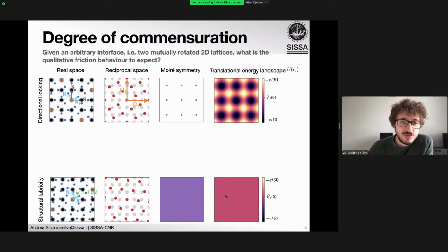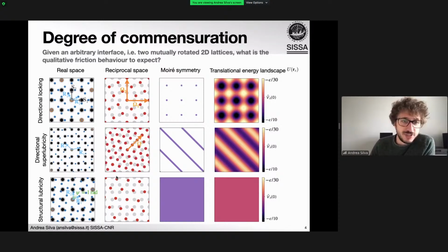And in this categorization, we discover an intermediate novel type of interface, which we call directional superlubricity, because for specific lattice symmetries, you would have only one coincidence lattice vector, and the moire pattern would be a form of dense lines spaced over discrete spacing, which results in this energy landscape, which is made of valleys and ridges, where the friction is exactly zero along this valley, but retains a finite value perpendicular to it.